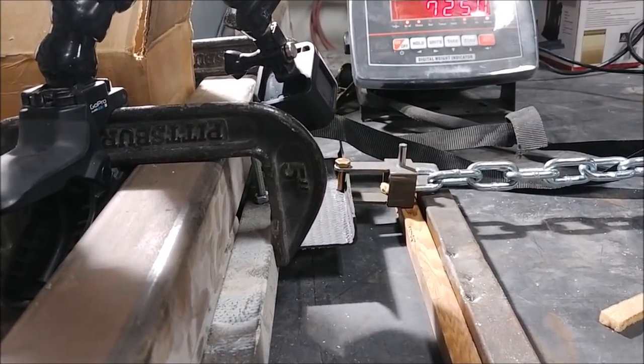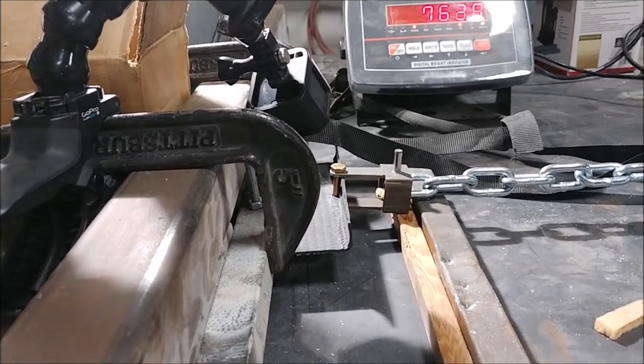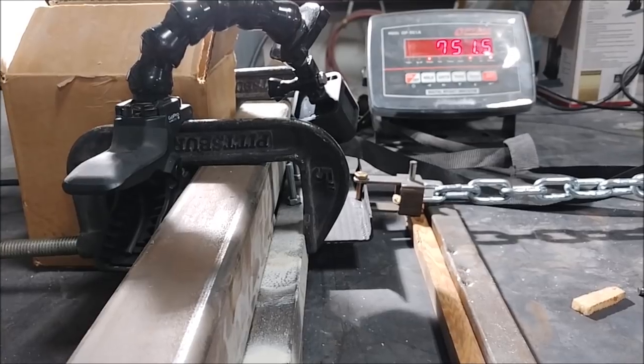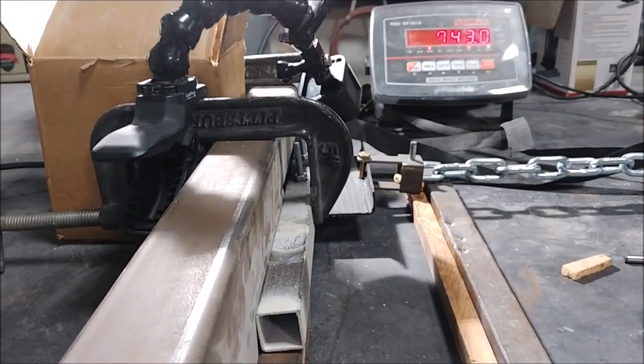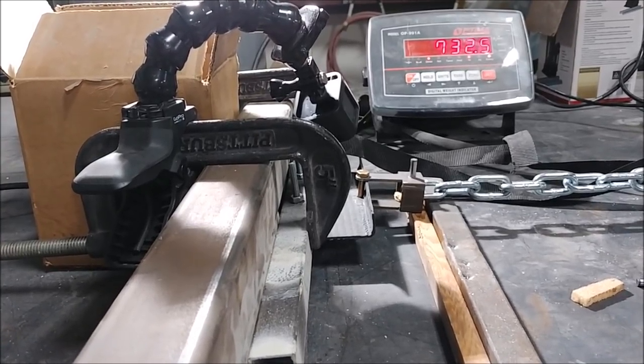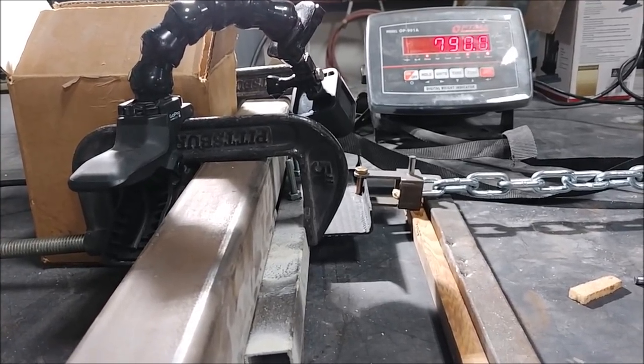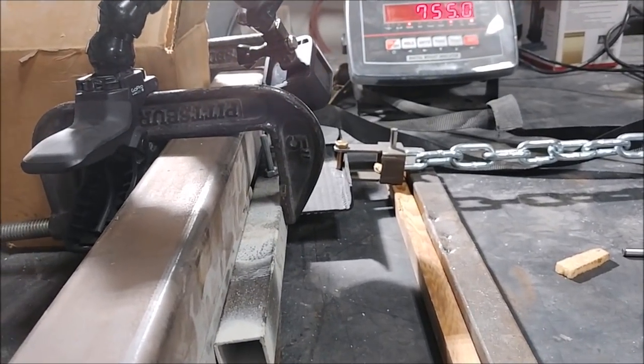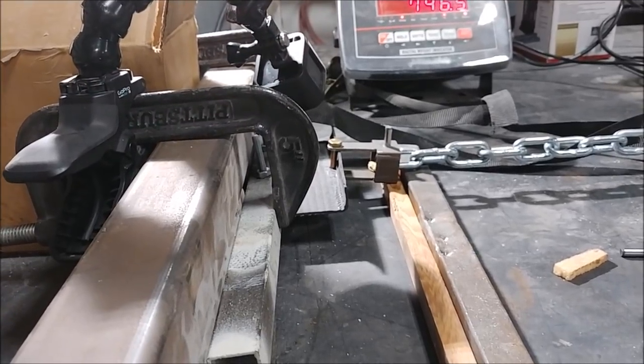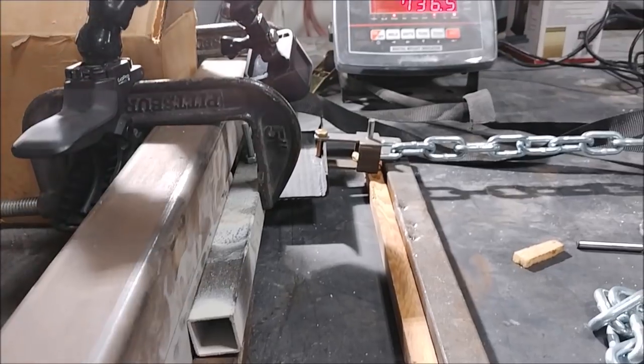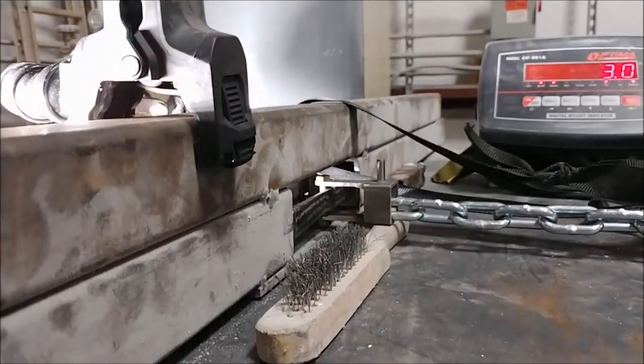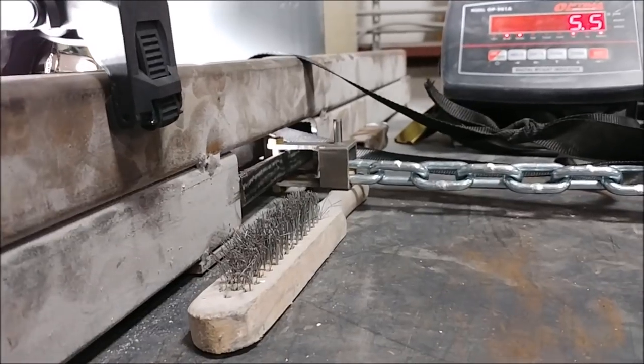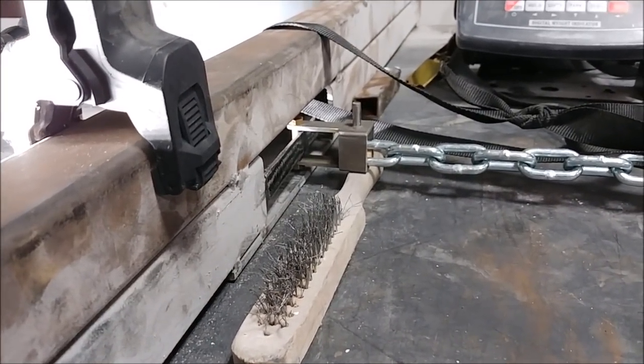What's interesting is this is just fresh carbon fiber, only laid up last week using one of our door molds. It hasn't been post-cured yet, which makes it way stronger when you bake it - that's what we're doing for everything. We're up to almost 800 pounds of force. The way Jeff has it clamped, it looks like it might come off the clamps, so we decided to put it back through the holes the way we had it in past tests.